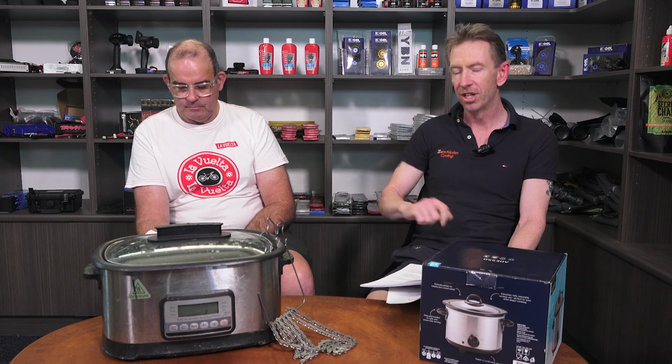Above 100, it's starting to get above the wax's happy temp. The wax may start to fume if it's getting to about the 110 degree mark. So try to keep it under 100. But again, slow cooker on low, lid off, you can't overheat it. You can't go wrong. So you don't need a thermometer. Just come back whenever it's melted, swish it, and you're golden.